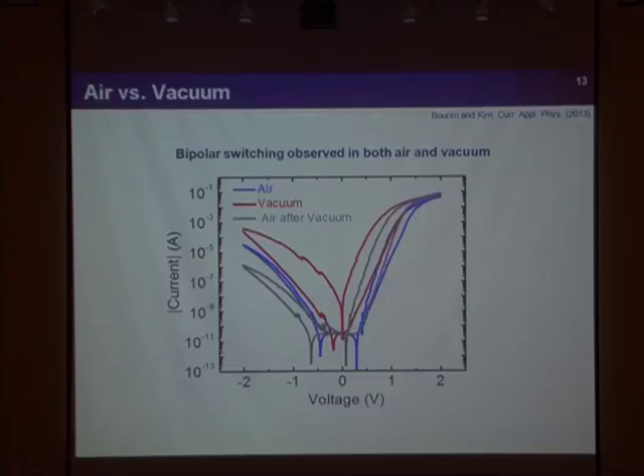So I continued another experiment, comparing the switching behaviors in air and vacuum. At first the switching is not that clear, the blue one. If you put the sample in vacuum, the switching is much clearer and its width is much bigger. When we come back to air, switching is more like the previous one. So it's a reversible change. How do we explain this?